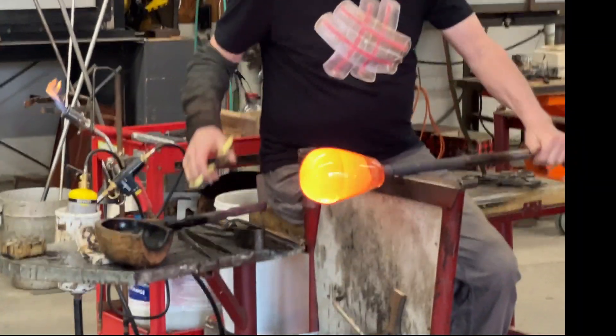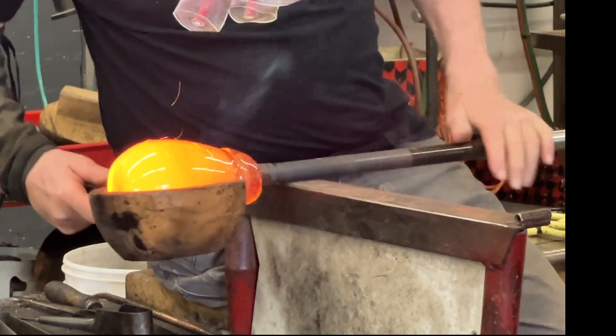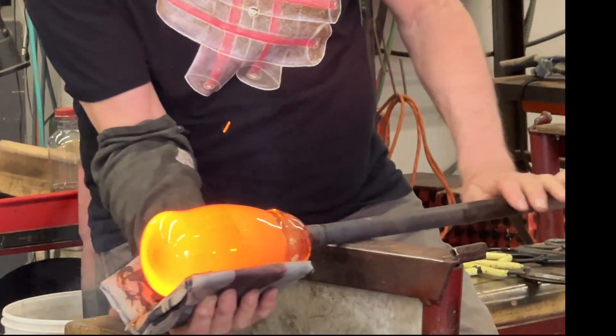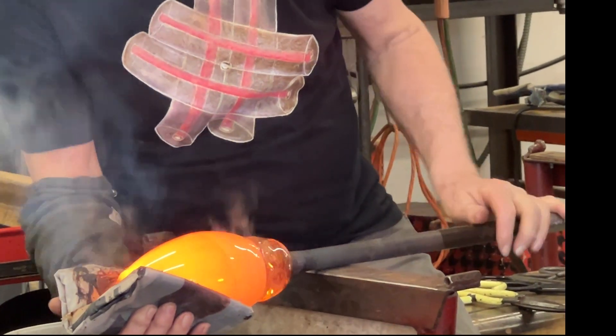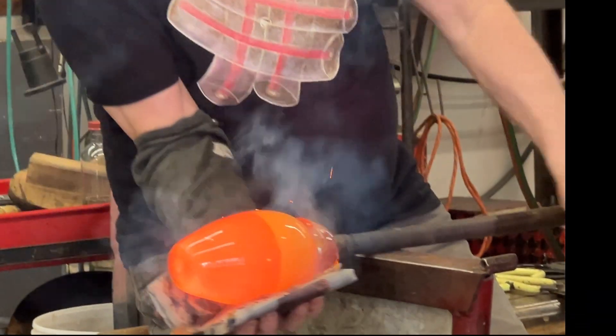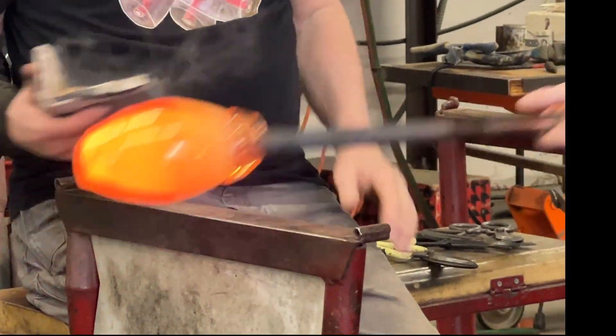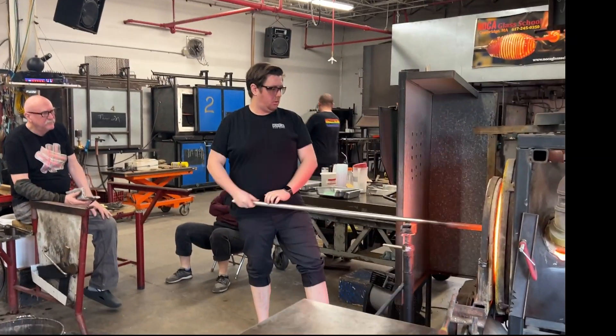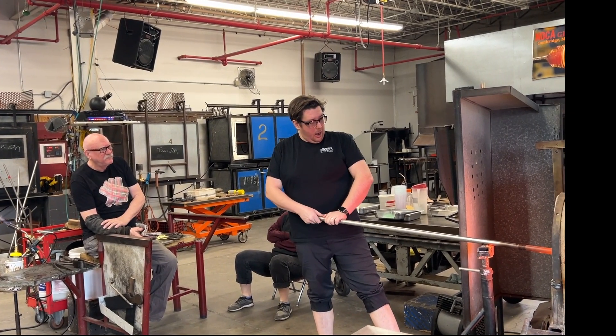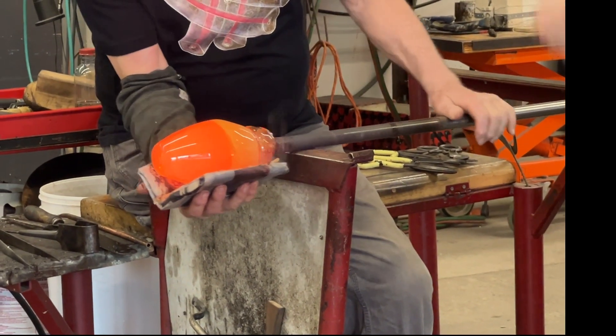I have a bubble — he still has a bubble! Sometimes there might be a bubble in the clear glass. You can see that by the time Henry goes back over, that center bubble had already got more. When he uses the block after the gather of glass, that's called equalizing the temperature — you're trying to equalize the temperature on the outside gathered glass with the inner part. Because if the inner part is cool when you blow, it's just not going to work. The temperature of everything in there has to be correct.